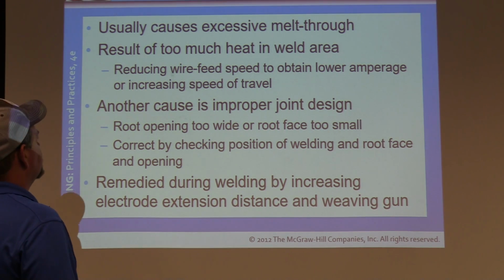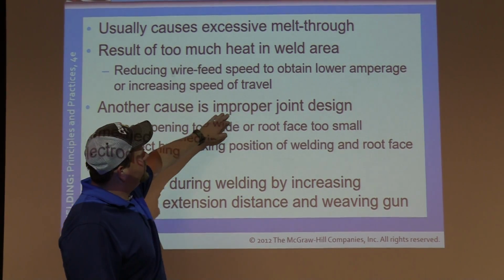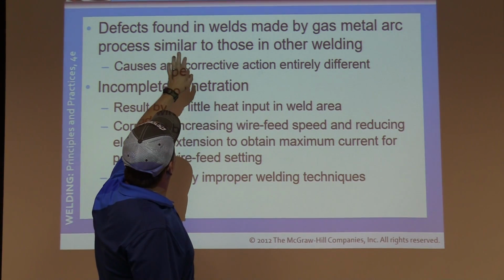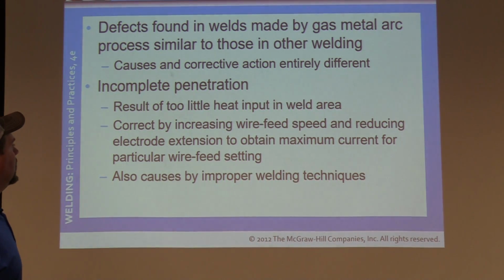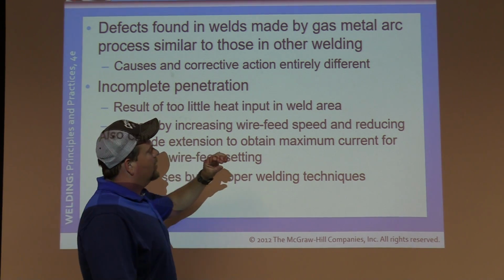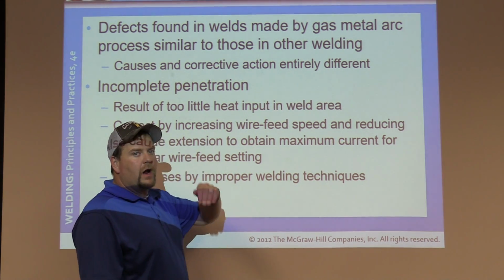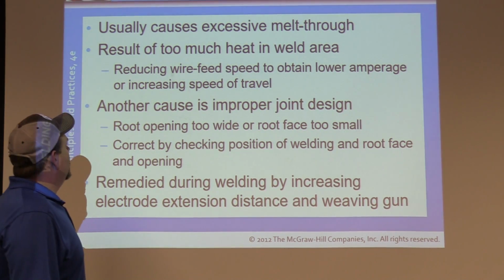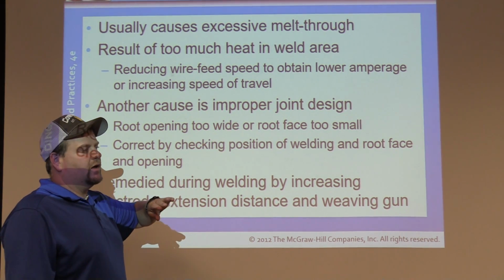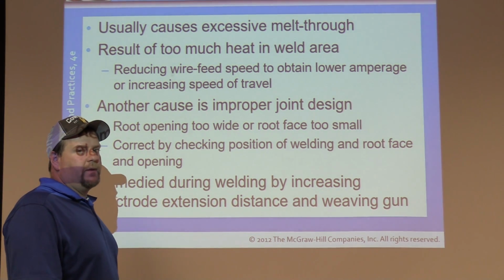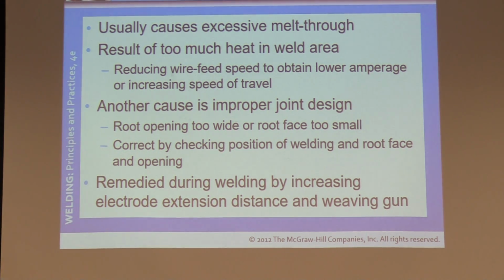Another cause is improper joint design. Okay, and improper joint design can be for excessive penetration. It can also be for incomplete penetration as well. If you're trying to do a square groove weld on a piece of metal that's too thick to do in one pass, you need to make sure to grind it back and prep it correctly. Okay, open it up to where you can get a good joint penetration to the back side. If it's 1/4 inch and you have to grind it back down and do it in 3 passes versus 2, that's a lot better for getting good penetration and good fusion along the entire weld, okay?